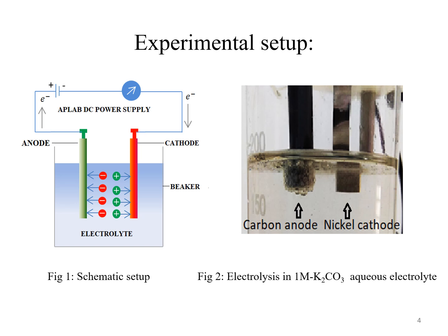A high quality graphite, which is naturally obtained, is a must for reproducing the results, as a normal graphite rod may be a mixture of clay, graphite and various other polymers and hence disintegrate soon in the solution during the electrolysis process. For the cathode, we focus mainly on pure nickel in most of our experiments, as it is corrosion resistant and is available in standard shapes and sizes. Besides nickel, we also study pure copper and alloys like nickel iron and Kanthal.